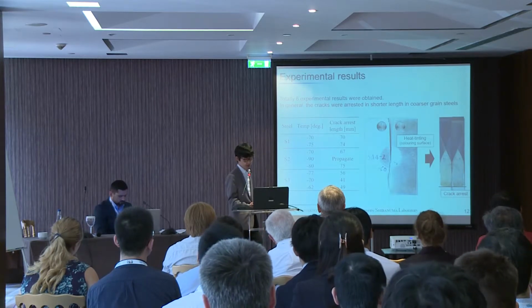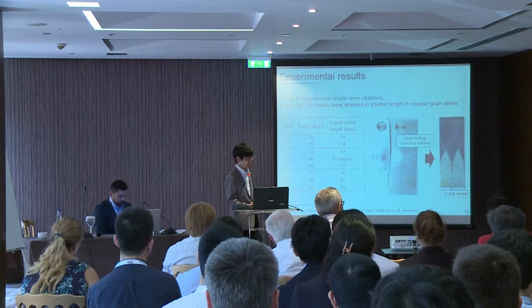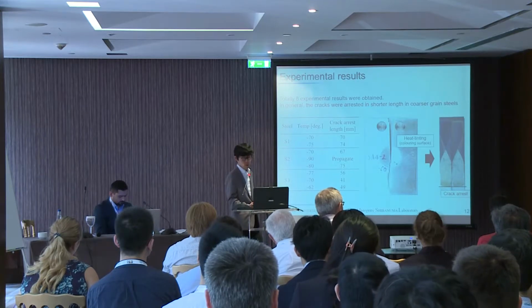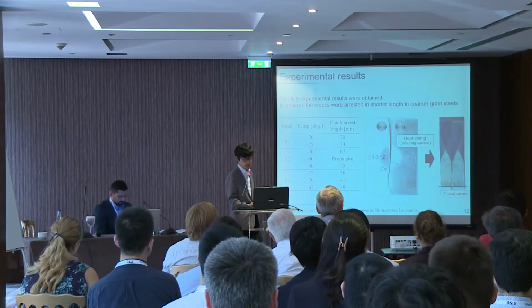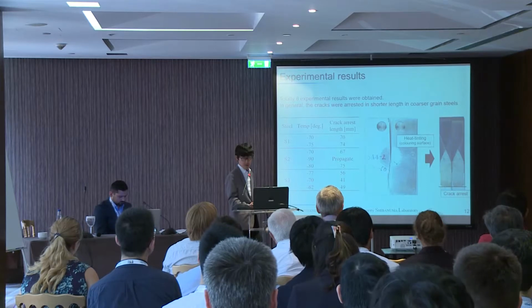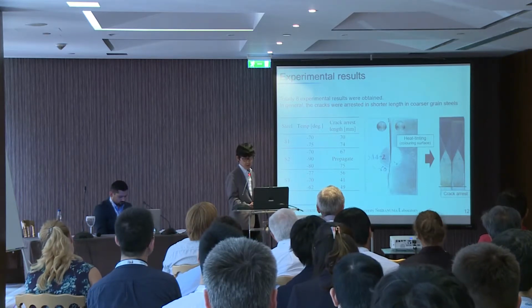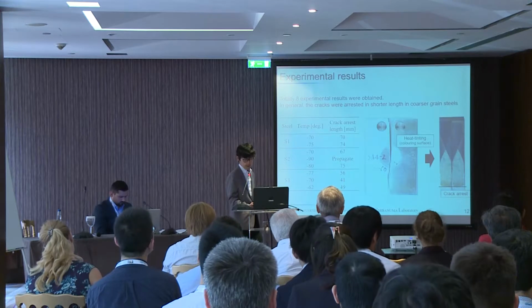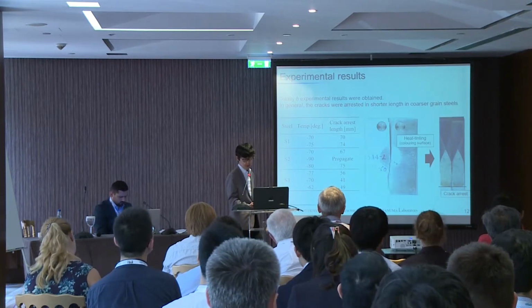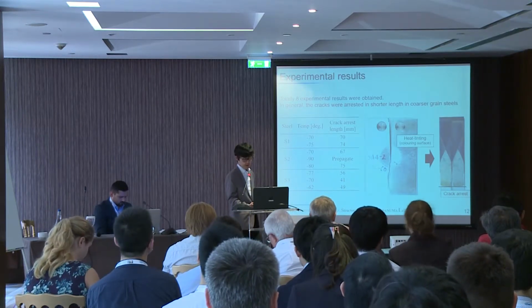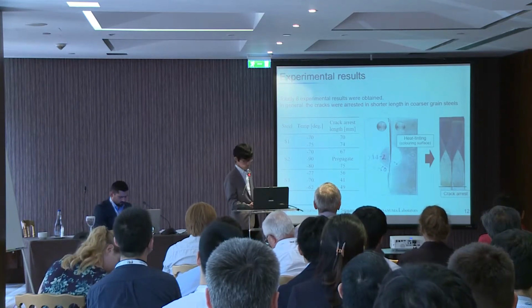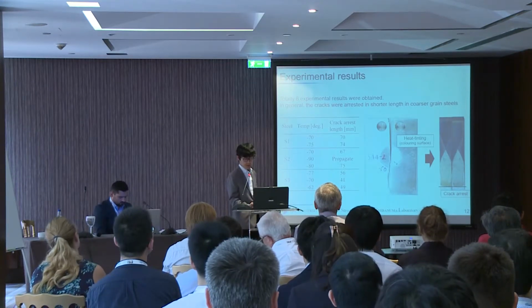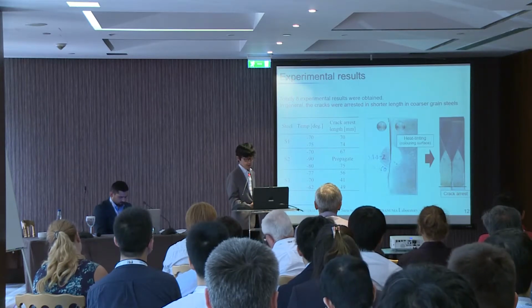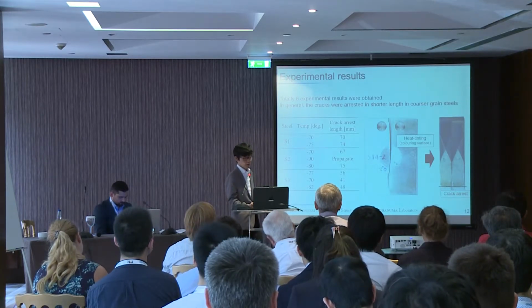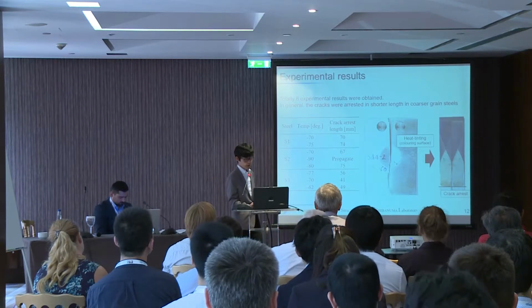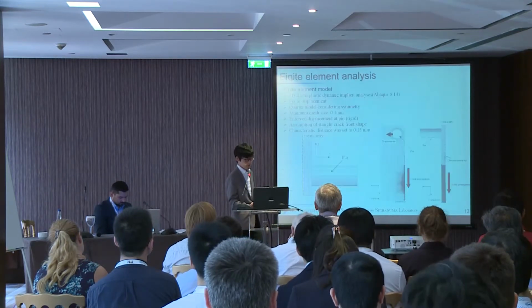Cleavage fracture surface were obtained by breaking ligaments after crack arrest. However, it is hard to distinguish crack arrest points, so heat tint was employed after crack arrest to color cleavage surface. And in practice, we measured crack arrest lengths after heat tint. In general, the cracks were arrested in shorter lengths in coarser grain steels.